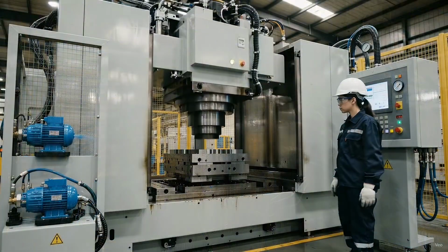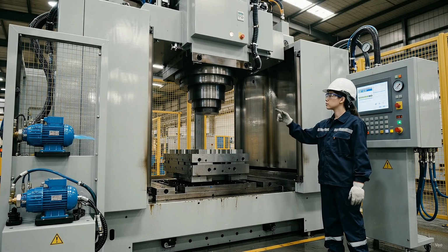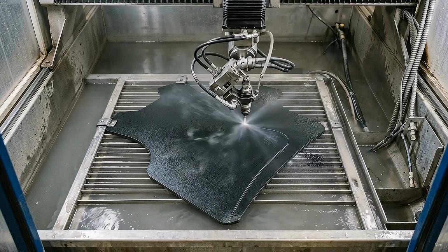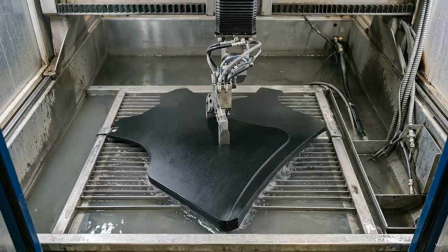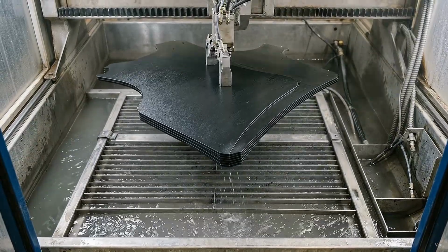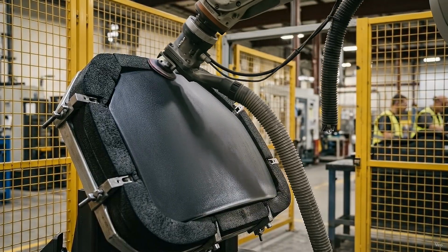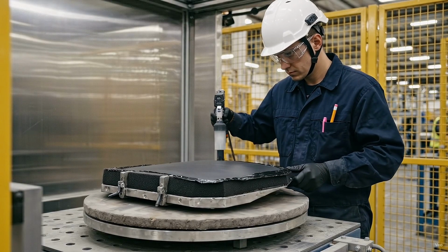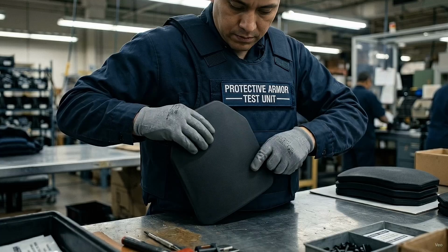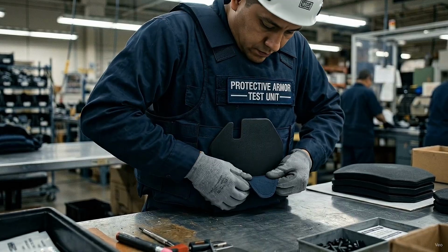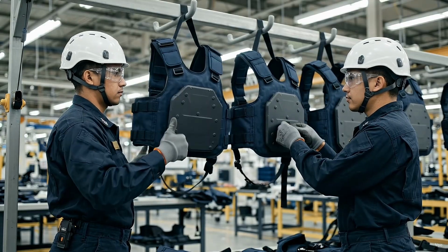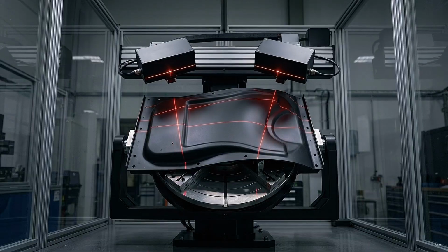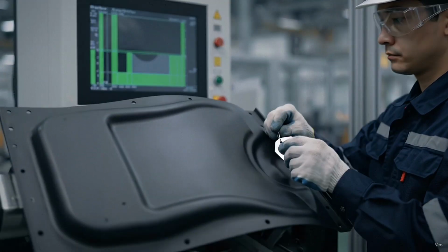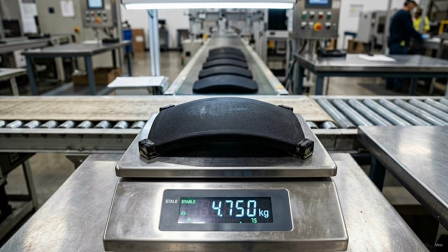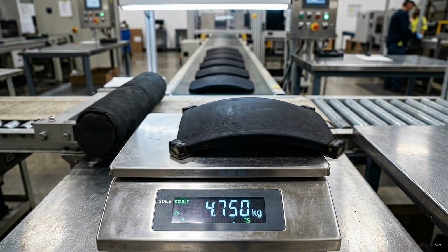Ultrasonic systems would map the interior without cutting the plate open, exposing hidden voids, weak bonds, and delamination. Environmental chambers would condition samples in heat, cold, and humidity to test whether the bonded structure remained stable. Other samples would be flexed and dropped to reveal edge weakness before ballistic evaluation. In a sealed laboratory tunnel, standardized projectiles would strike plates mounted against instrumented backing material. High-speed cameras and sensors would record penetration, deformation, fragment behavior, and the way energy spread through the layers. Because ballistic tests destroy the samples, they would represent validated production groups rather than every saleable plate.